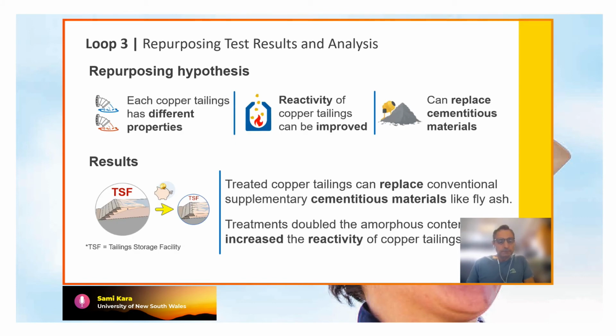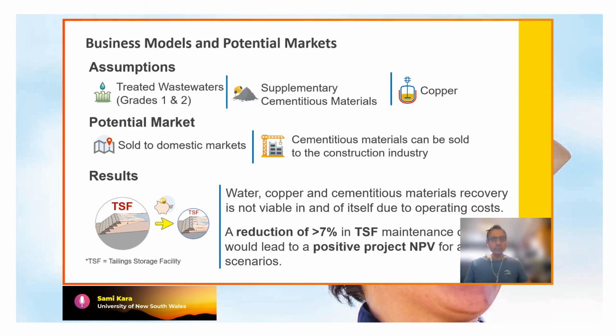For the repurposing, the results show that the treated copper tailings can replace conventional supplementary cementitious materials such as fly ash, and treatments double the amorphous content and increase the reactivity of copper tailings. Based on these, we looked into several business models and potential markets, and our results indicate that the water, copper, and cementitious material recovery is not viable in and of itself due to operating costs. A reduction of 7% in the tailing maintenance cost would lead to positive project net present value for all scenarios.